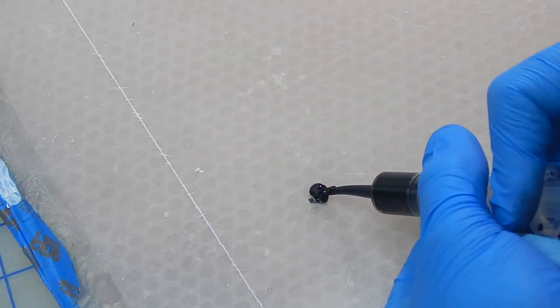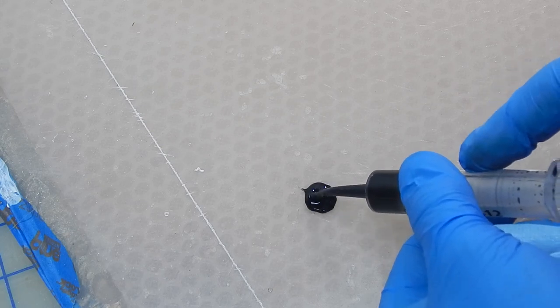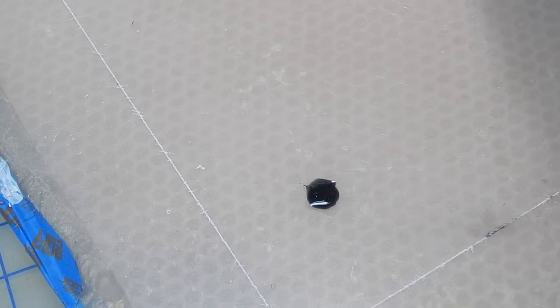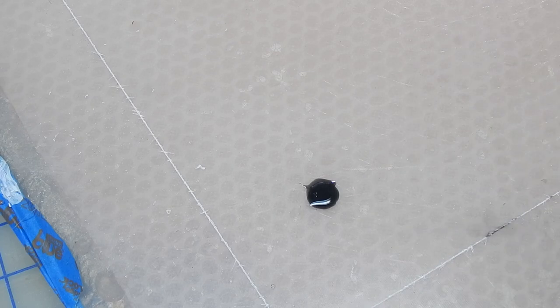Whereas if you try just filling it the air that's in there already will block it off. There's no way for the air to get out so the resin can't displace the air. Something like this I'm really just pumping a cell full of glue. But it's a look at how to do a pretty quick and simple void repair with a syringe.